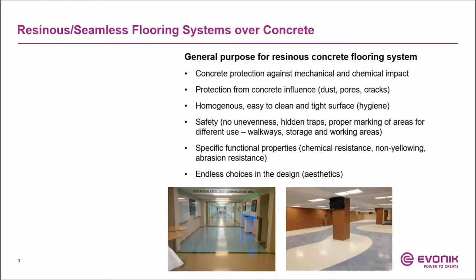Also, safety is another reason. By applying some kind of self-leveling coating on the surface of concrete, you're able to even out the surface, forming a smooth surface. And also, you're able to designate certain areas by markings. So you can designate the use of walkways, storage, and working areas, again, through marking on the coating itself. Also, specific functional properties like chemical resistance, yellowing resistance, and abrasion resistance can be improved through the use of resinous or seamless flooring. So all these reasons I gave you were functional reasons for putting a coating down, but there's also the aesthetic reason. No one wants to look at bare concrete itself. You really want a nice design. So there's also an aesthetic reason for applying the coating on the surface of the concrete.